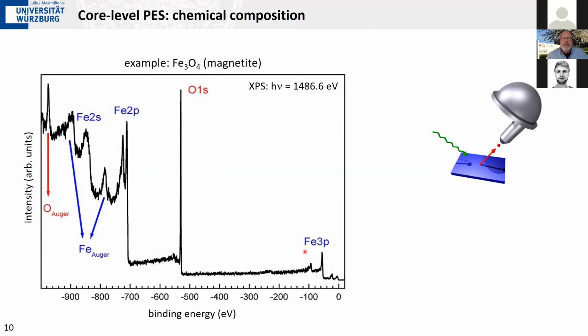And you see these characteristic peaks in the spectrum, and these can be identified as simply the core electrons. So here we have the iron 3p core level. This is the spin-orbit split iron 2p core level, iron 2s. Here, this very sharp line at about 530 electron volt binding energy is just the oxygen 1s core level. And very often you have some additional features in there, which are assigned here.